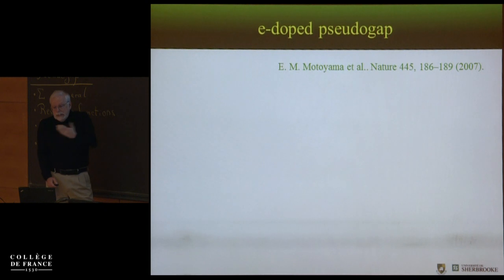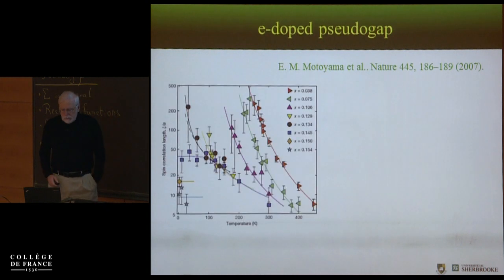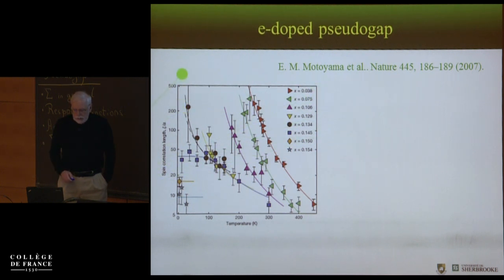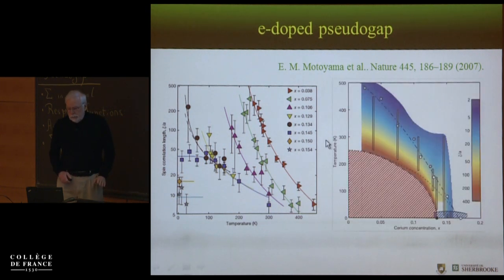So is this observed experimentally? Well, the group of Greven, when he was at Stanford, did detailed measurements of the antiferromagnetic correlation length as a function of temperature in NCCO, which is an electron-doped cuprate. Whatever the details here, I just plot their results. So this is temperature, this is doping, and the color is the size of the correlation length.